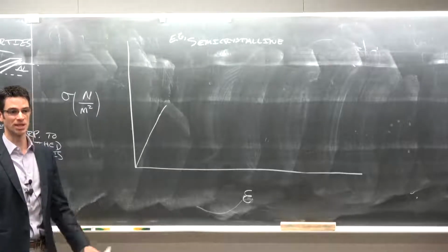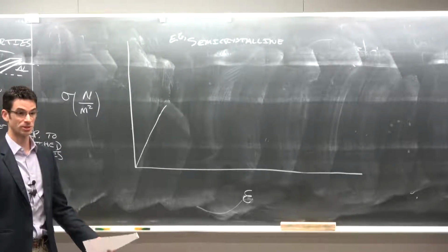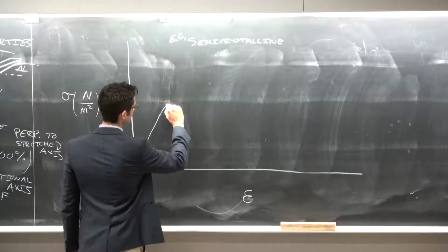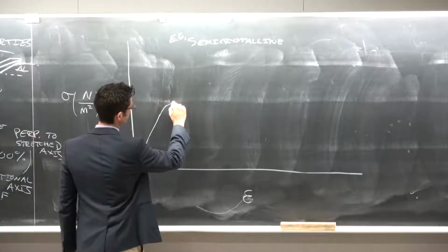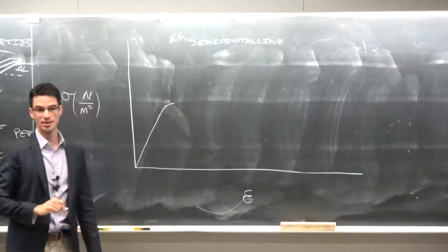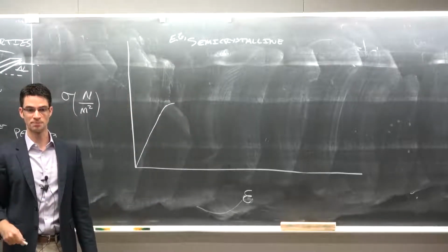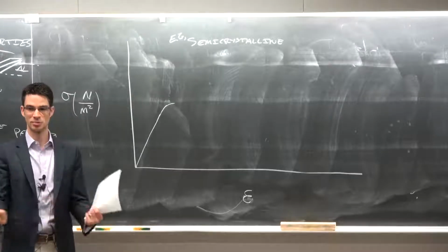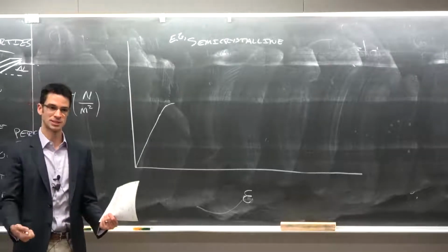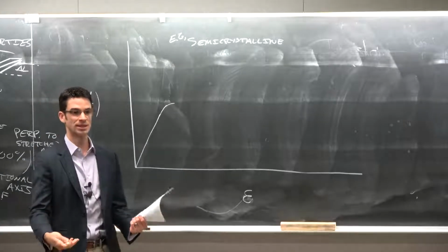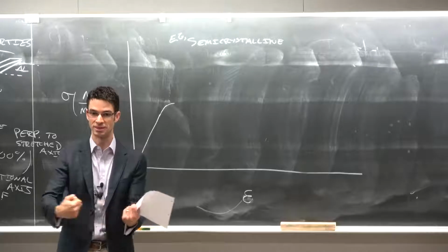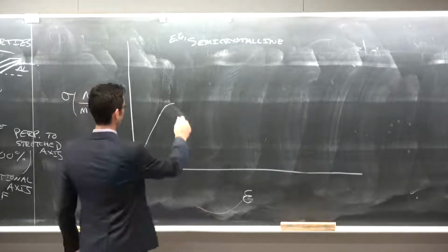We've passed the proportionality limit. Then something happens where the polymer sample yields. Now, what happens at the yield point? At the yield point, the polymer crystallites start to pull apart. We put in enough force to break the intermolecular forces between the polymer chains in the crystallites, and we can now stretch the material out that way.